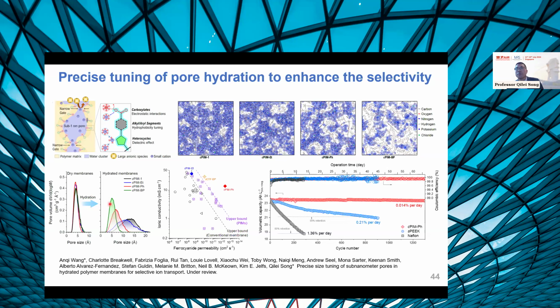This was done by molecular simulation by Professor Kim E. Jeffs. As expected, if we are able to tune the hydrophobicity and the selectivity of the membrane, we got much better performance. You can see that the battery was able to cycle for 2 months with minimum decay. This is much better compared to traditional membranes like SPEEK, for example.